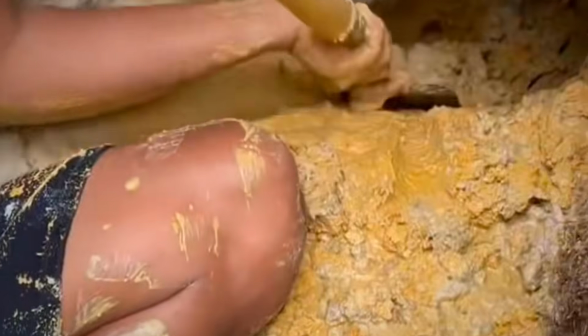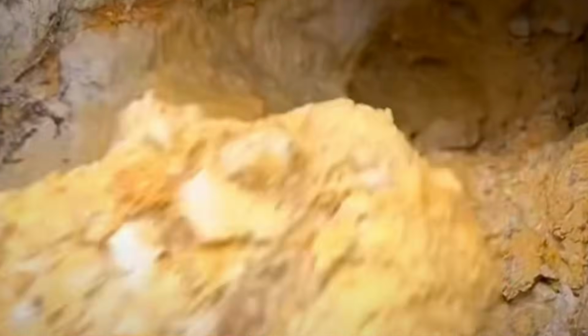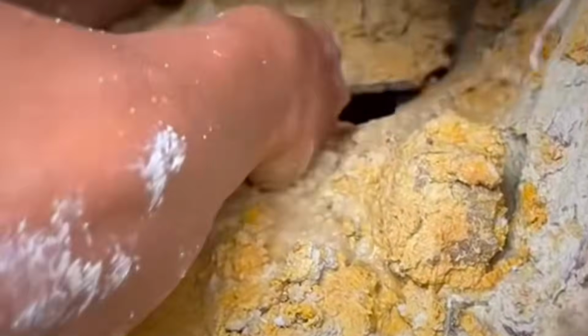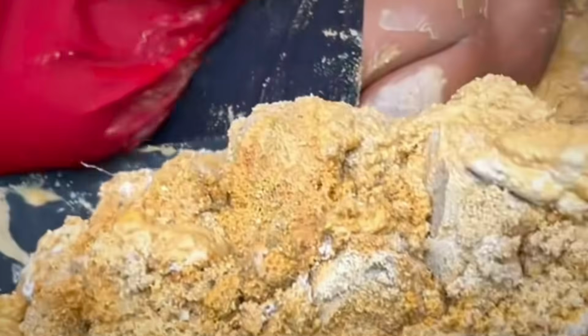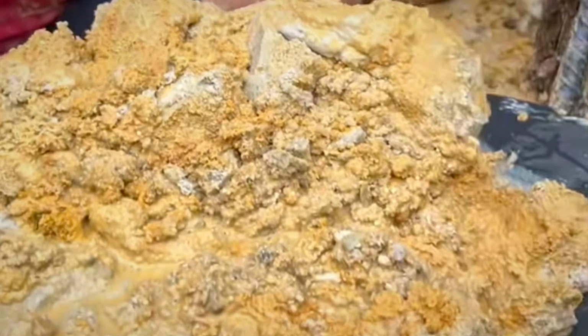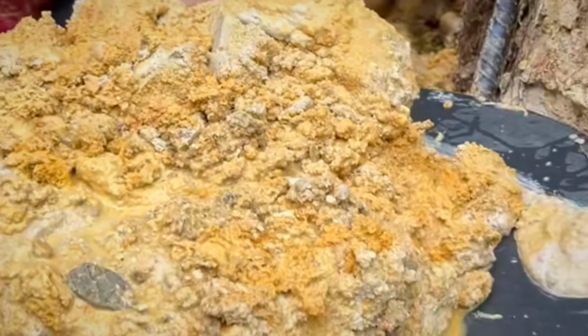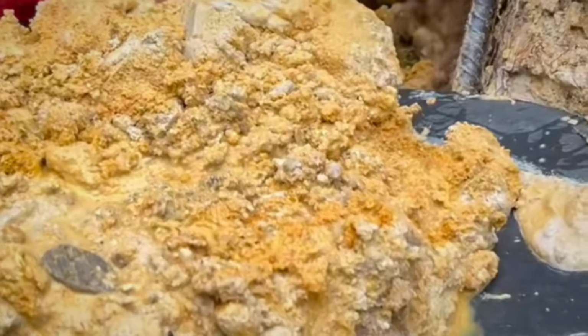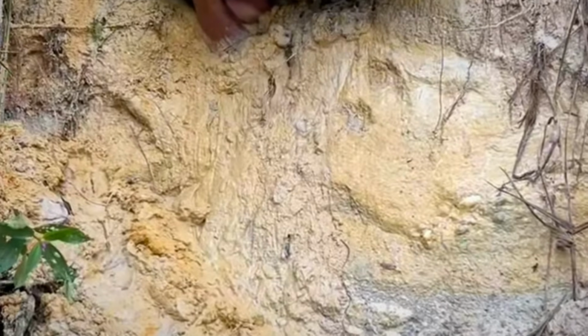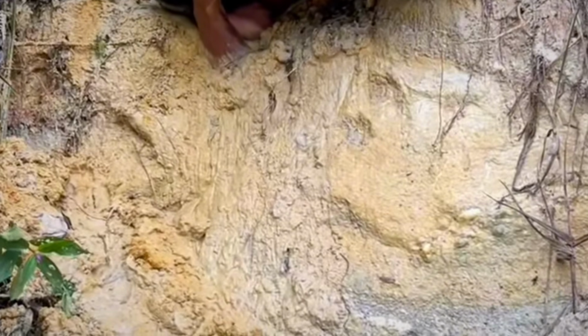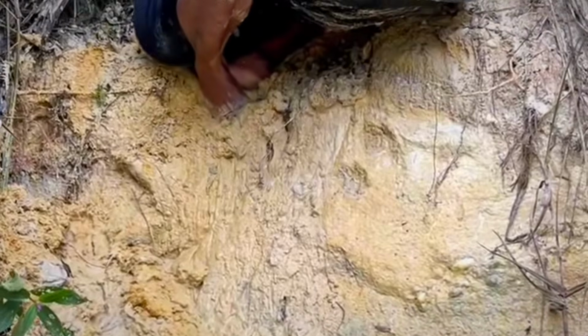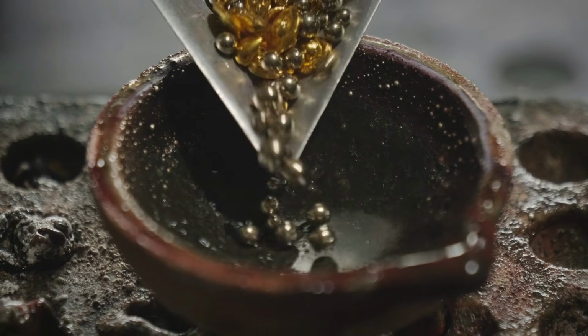In productive zones, even a single pan test might show visible results: flakes, specks, or a yellow tail in the pan's bottom edge. But absence of gold doesn't mean absence of value. If the concentrate is rich in sulfides, the gold may be refractory, demanding lab analysis to confirm. Conversely, if everything washes away and no heavy residue remains, that quartz likely holds little more than silica and hope.